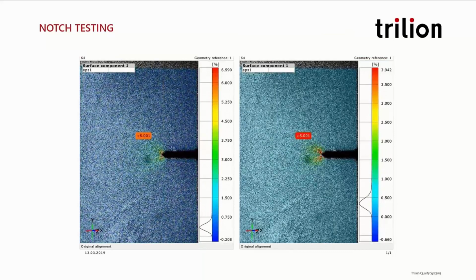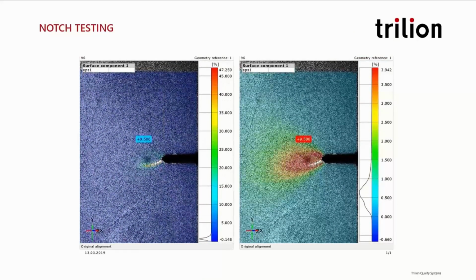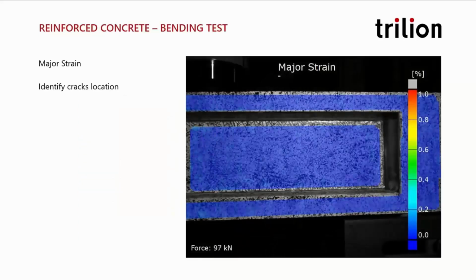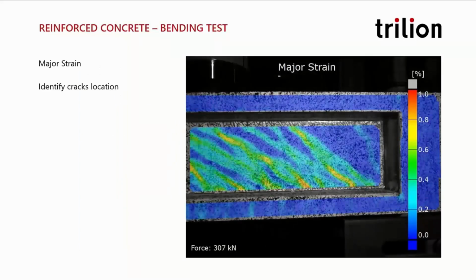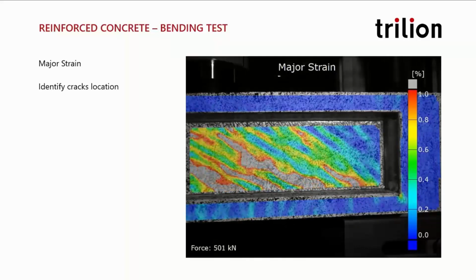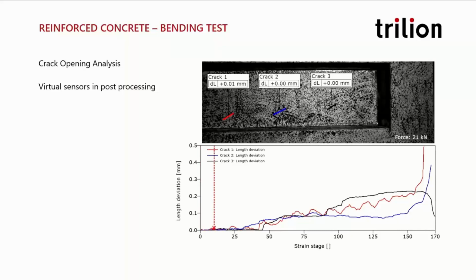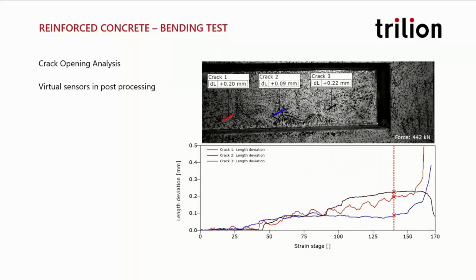Then you get into things like fracture, and fracture, of course, is very complex, and understanding how it's going. One of the powerful tools is that not only are we measuring mode 1 characteristics like a clip gauge could measure, but we can measure mode 2 and mode 3 just as easily along the entire length of the crack. And so in any application, even in the field. Another good example is instead of having a notched specimen, you can just run a fracture test and watch how your cracks are propagating. And then after the fact, put down your displacement sensors and measure the displacement of the cracks that developed. You're seeing the data after it's happened, and now you're able to measure precisely what's happening to the component. Once you know the final result, you can put your gauges down after the fact.